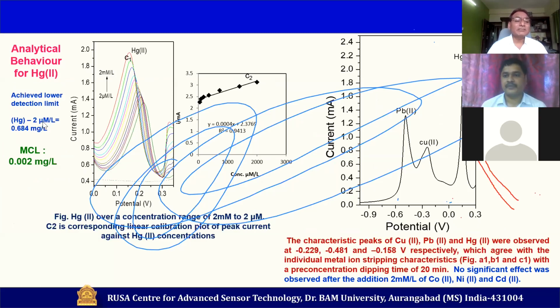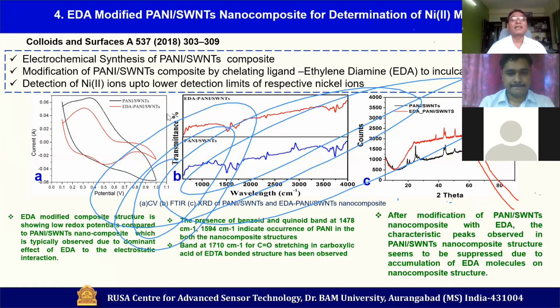And then we have also tested the same structure for detection of mercury also. For mercury, although MCL is 0.002 mg per liter, we could reach 0.6 low detection limit. Very close to that, but still it was better than what was reported at that time in the world. That is why we could publish the data. And then we have also explored this with EDA, right? So Pani, again polyaniline SWNT, with EDA. So we thought, we tried EDTA, now let us try EDA.